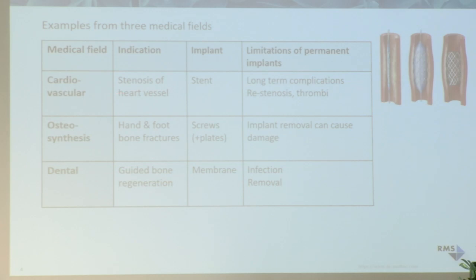So if you have arteriosclerosis, you have a narrowing of your cardiac arteries, you go in with a catheter, you expand the balloon, you destroy the plaque, and on top of the balloon you have this metallic scaffold, which is permanently deformed and keeps your vessel open. Now in the long term, this can have a big problem, and you may end up with restenosis, a narrowing again, necessitating another intervention. Or if you coat the stent with drugs, you have less restenosis, but you may have thrombus formation instead.